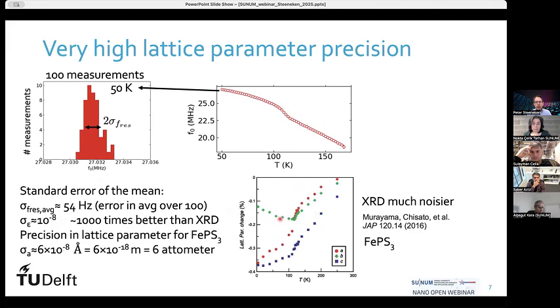So here on the right side, for comparison, I've shown an X-ray diffraction measurement of the same material, and our measurements are a factor 1,000 times better, which actually provides us with an accuracy of the lattice parameter of 6 attometers. So we can really see very small changes in the distance between the atoms. I didn't mention that yet, but we have chosen this material because this is one of those antiferromagnetic 2D materials.